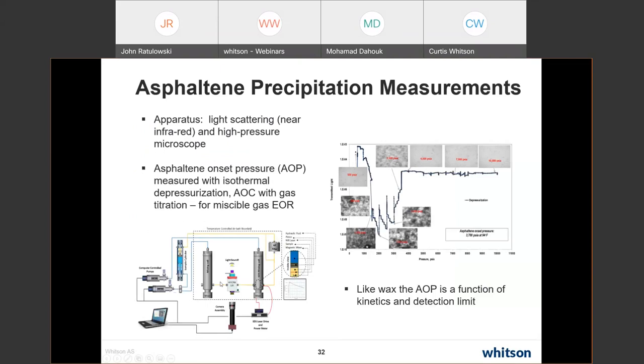I pulled pictures from the DBR lab because that's where I have the pictures from, but it's pretty much the same. They'll look at light scattering in the near infrared, and also usually you have a high pressure microscope for visualization. Asphaltene onset pressure is measured with isothermal depressurization, and you can measure an AOC where people will titrate with gas. This is usually done for miscible gas EOR or for injection gas for gas lift.